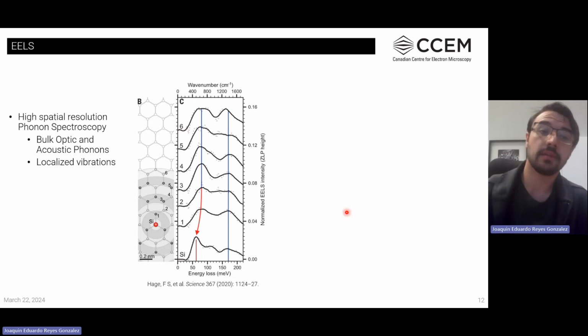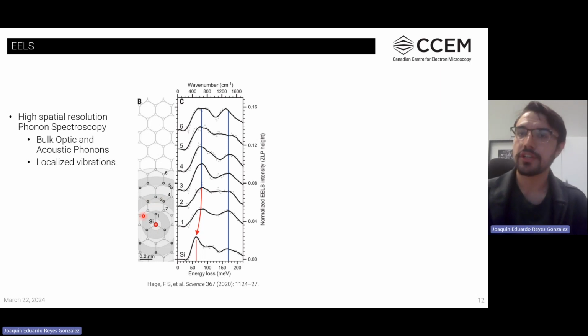Here we have a great example, which is really exciting: having just a single silicon atom impurity in a graphene layer. These types of experiments are done using a slightly different configuration of the optics in the EELS, called dark field EELS, where the main beam, the direct beam, is displaced from the entrance aperture to be able to collect localized inelastic scattering signal.